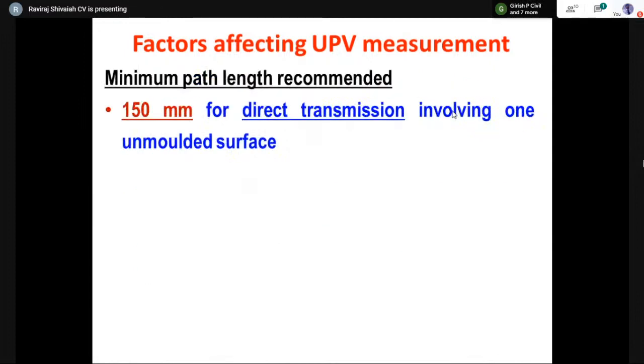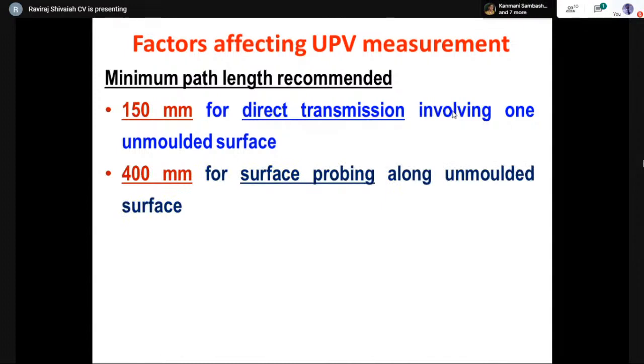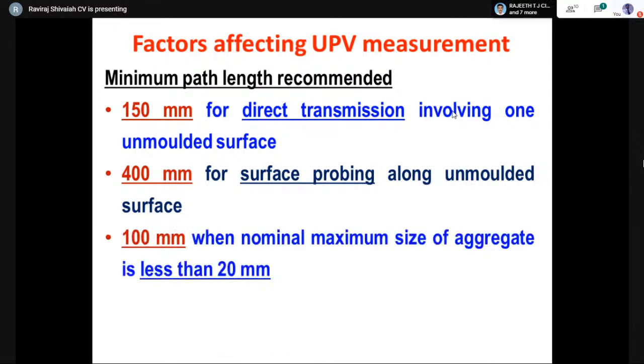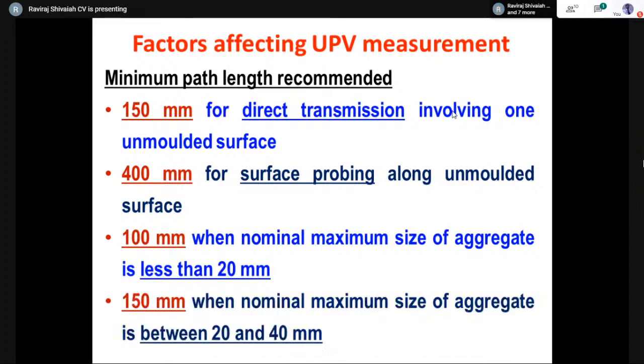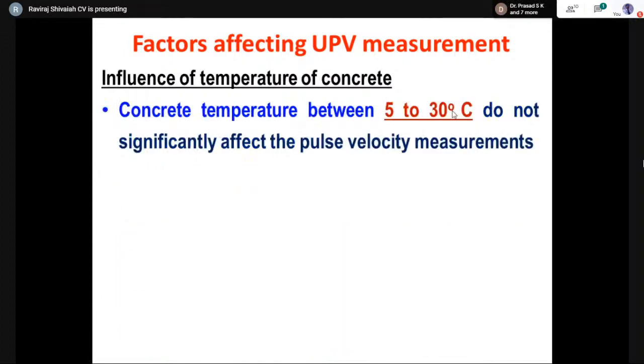Regarding path length, generally we say 150 mm at least in case of direct transmission, or 400 in case of surface transmission. If the size of aggregate is 20 mm or less, at least 100 mm; between 20 and 40, it is 150 mm minimum. What we are talking about is minimum distance, correct? So these are minimum distances. If you have greater than this, things are fine.